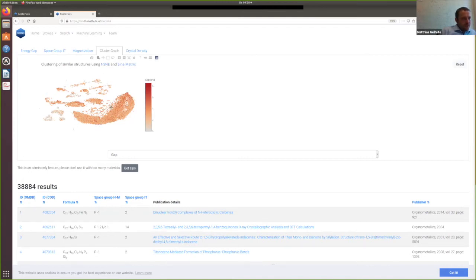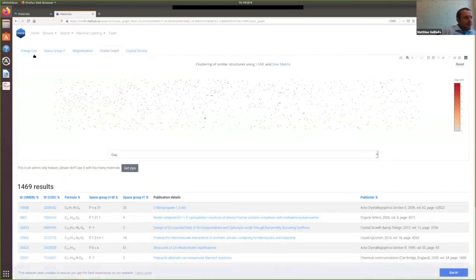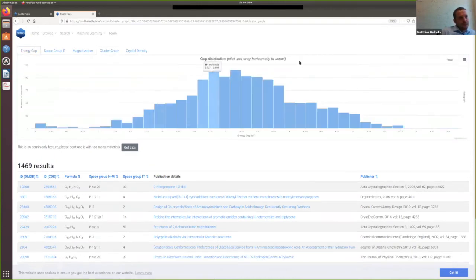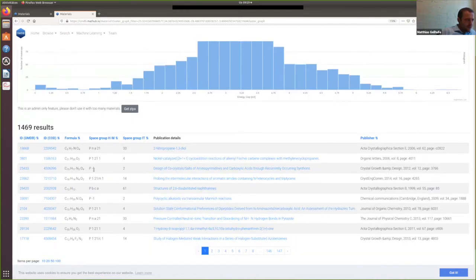And if I put an additional property on top, like the band gap, then I see that this banana actually corresponds to a class of pretty much high gap materials. So I can say, okay, let's select a part in this banana and take a look at how the band gap distribution looks for these materials. And then I see that in this part, I pretty much get all the materials which belong to this Gaussian band gap distribution that I've seen in my initial plot. And I have about 1,500 materials. So it's a regime where I can say, okay, it's large enough to say something about statistics.